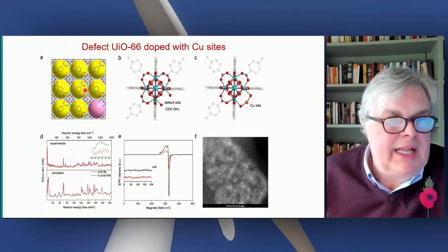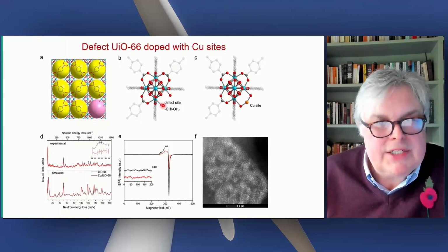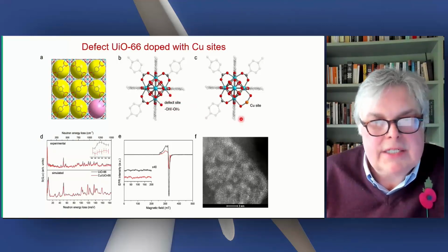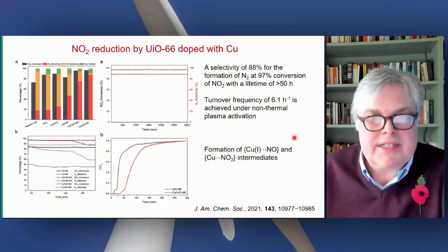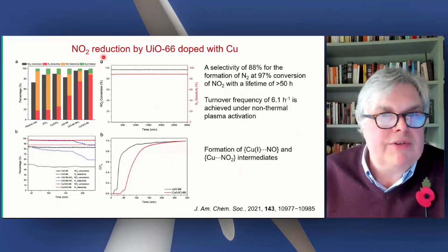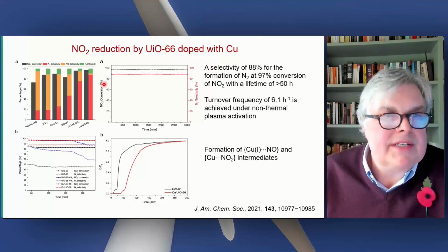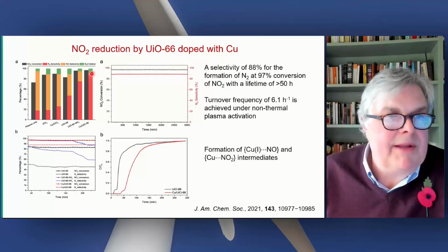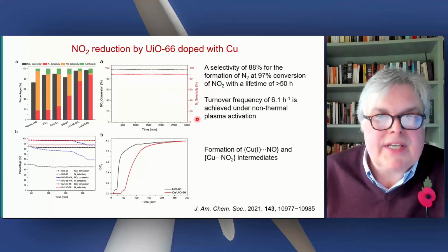One of the bridging ligands here is missing, and you can selectively make defect MOFs, which is another area we're working in as well. And this is very powerful because it releases two hydroxy water groups. You have a vacant site, you can put a copper in there. And what we have done with this system is, again, reduce NO2 using this, with better selectivity than before. Again, I emphasize this is under non-thermal plasma activation.